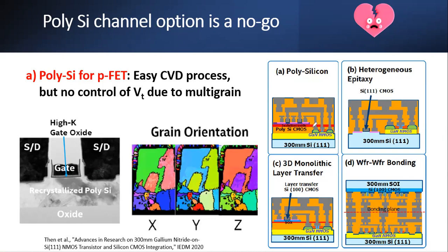Unfortunately, the way nature works is that it's done by a CVD process or at best ALD. No matter what you do, the best case will be polysilicon. And then when you do polysilicon, you anneal it and recrystallize. Initially you may be amorphous, but eventually you recrystallize it with high temperature. Then you form a polysilicon. It seems okay. Then you put your devices on top, high-k metal gate, source and drain, and all that. But what's the problem? Why does it say no go here?